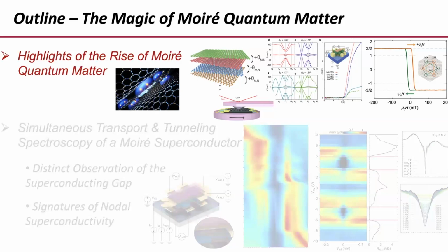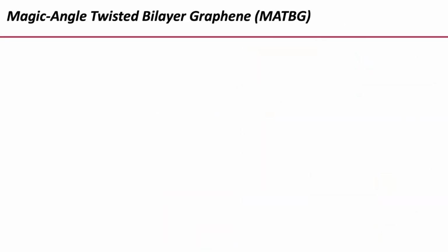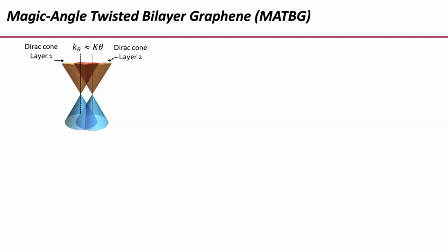So let me get started with this, and start with magic angle twisted bilayer graphene. So graphene has in the electronic structure Dirac cones, and if you have two layers, you have the Dirac cone of layer 1 here and the Dirac cone of layer 2. If the twist angle between the two graphene sheets is small, the Dirac cones of each layer are separated a small distance in momentum space, which is proportional to the twist angle. And this would be the situation that would be realized if the electrons in one graphene sheet did not know about the other graphene sheet, okay?